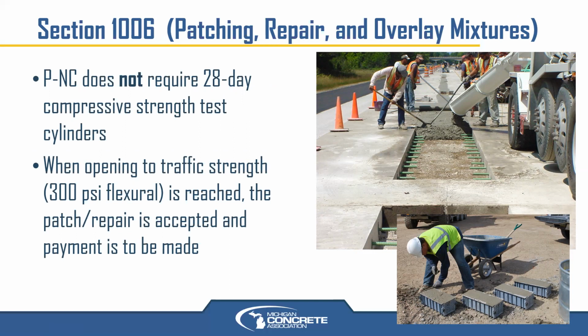So if you are doing one of these repair jobs of a concrete pavement using a P-NC mix, you should not see any compressive cylinders out on the job, whether they're 6x12s or 4x8s. You should only see what we have pictured in the bottom right there, which are the beams.